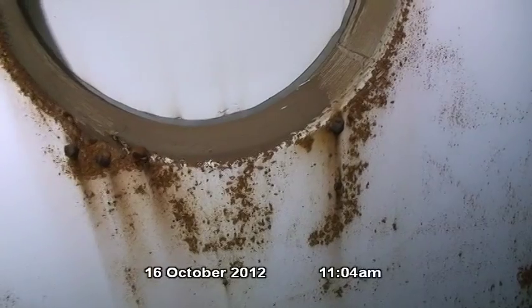Another corrosion nodule is present on a weld. Additional corrosion is present in many areas at the base of ring number 4. Again, the areas of corrosion on the shell number in the thousands. We've now reached the area where the manway is located on the shell. The interior of the manway is coated with epoxy. The epoxy coating is in fair condition.